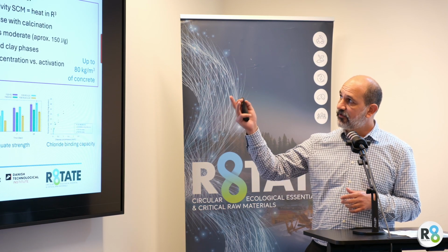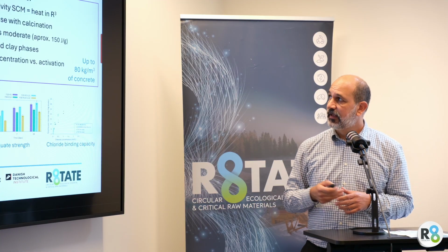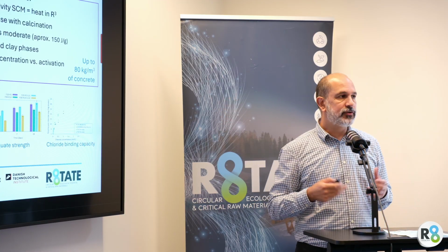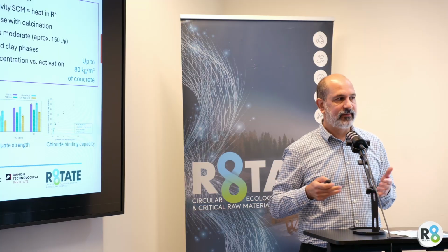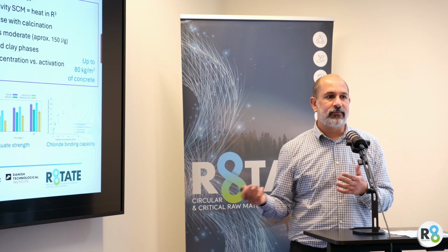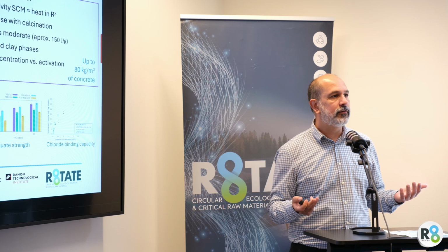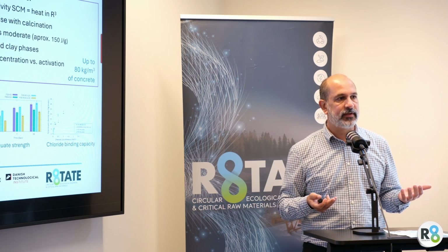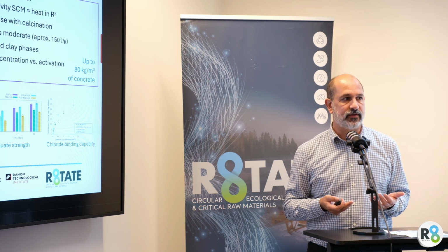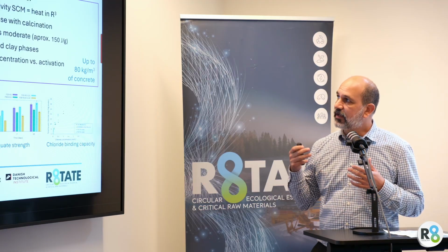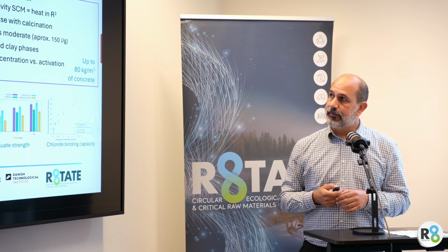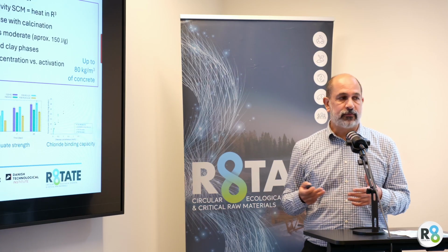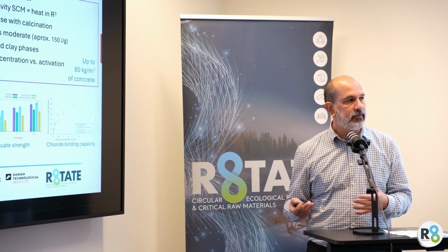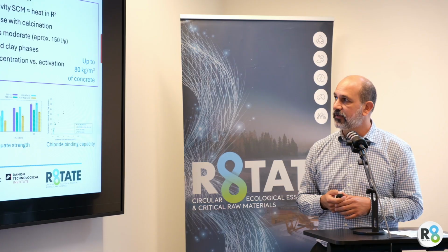So we reach reactivity levels of approximately 150 joules per gram. Probably that says nothing to you, but it's comparable to a siliceous fly ash, which is a supplementary cementitious material that is very present in the European market. So we can match the performance of a competitor that is very much used already all over Europe.